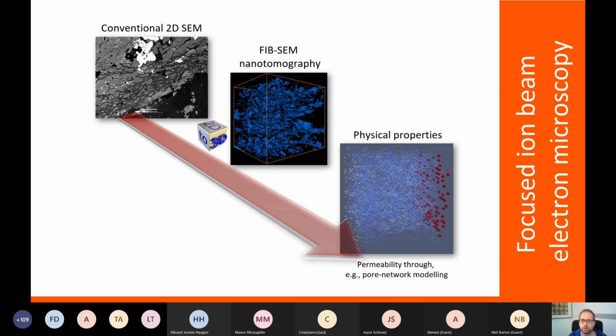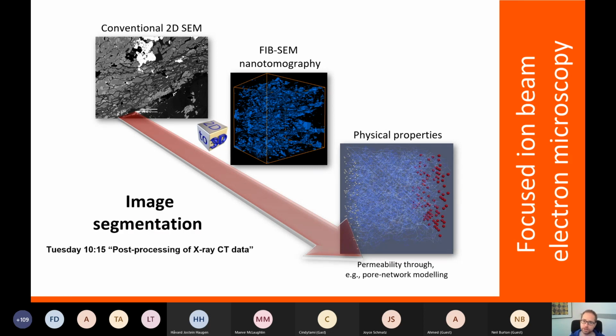But in general, you can go from conventional 2-dimensional SEM imaging, such as this backscattered electron image here that shows you the atomic number contrast, to 3-dimensional FIB SEM nanotomography, eventually to physical properties using numerical modeling. And we will learn more about how you go from images to 3 dimensions and visualization and data treatment tomorrow, because the techniques that we use here to visualize these 3-dimensional volumes are the same as in X-ray tomography. So there's actually a lecture tomorrow on image segmentation or post-processing of X-ray CT data, which will also be applicable for the data that comes from a focused ion beam scanning electron microscope.